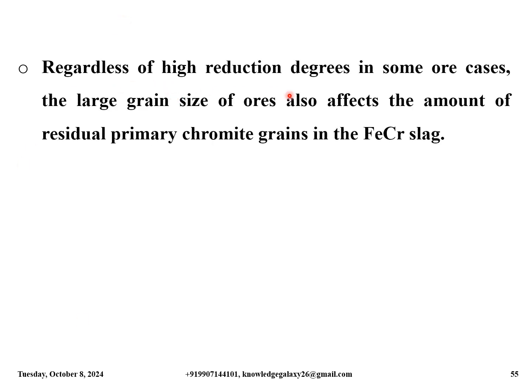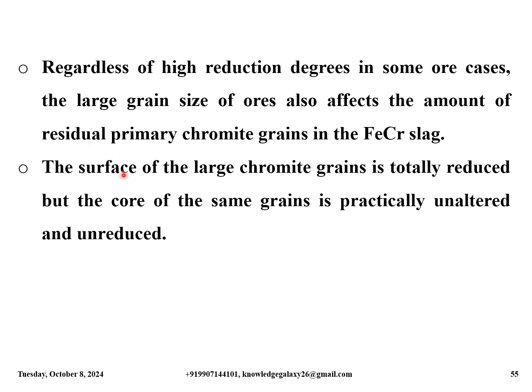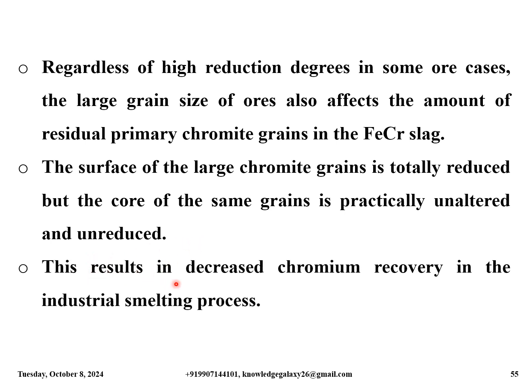Regardless of high reduction degrees, in some ore cases, the large grain size of ores also affects the amount of residual primary chromite grains in the ferrochrome slag. The surface of the large chromite grains is totally reduced, but the core of the same grains is practically unaltered and unreduced. This results in decreased chromium recovery in the industrial smelting process.